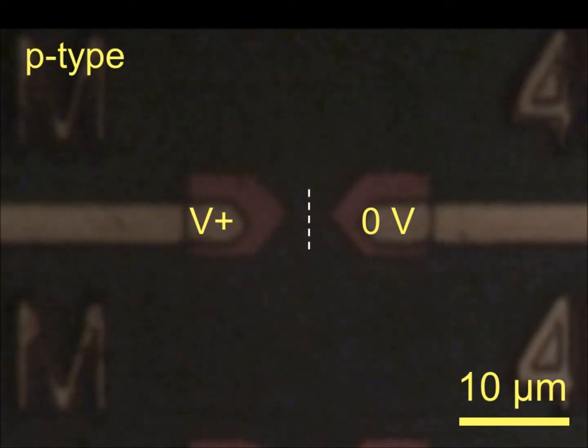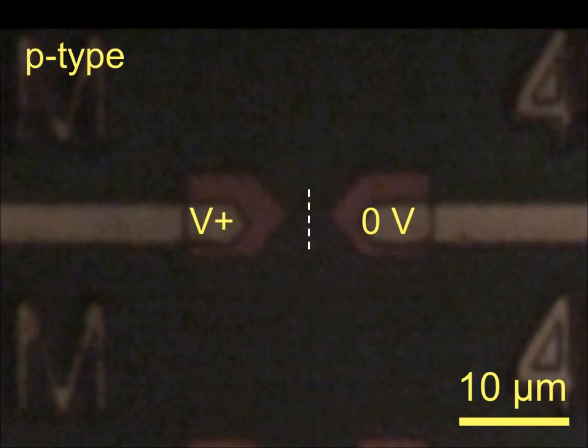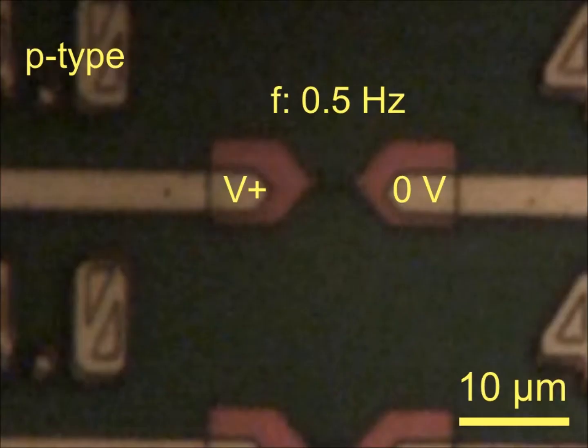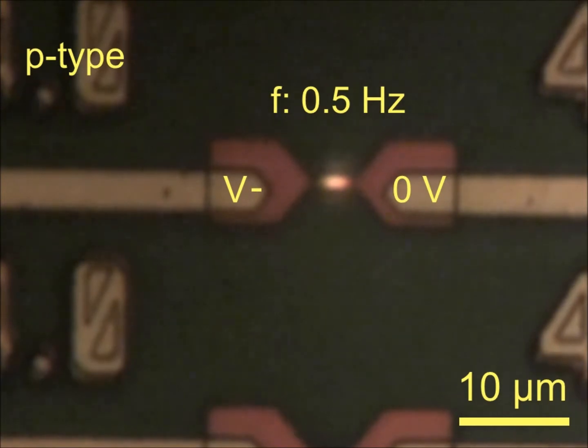As the wires emit light due to self-heating, the hottest spot on these p-type wires was observed to be shifted away from the wire center and towards the source of the majority carriers. The asymmetry in light emitted from the wires is more visible when the electrical current direction on the wires is alternated. For this case, the hottest spot location alternates with current direction, proving carrier and heat transport are coupled.